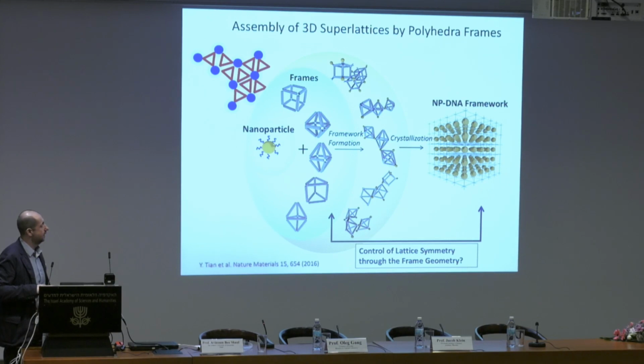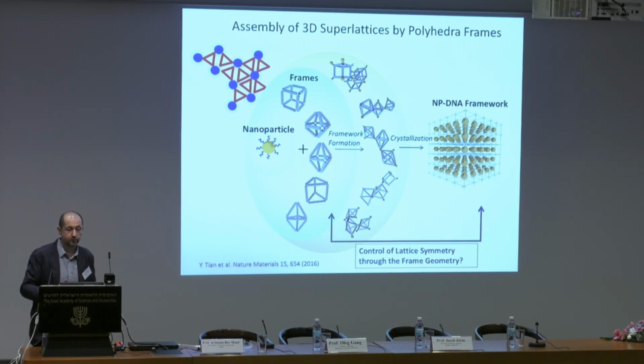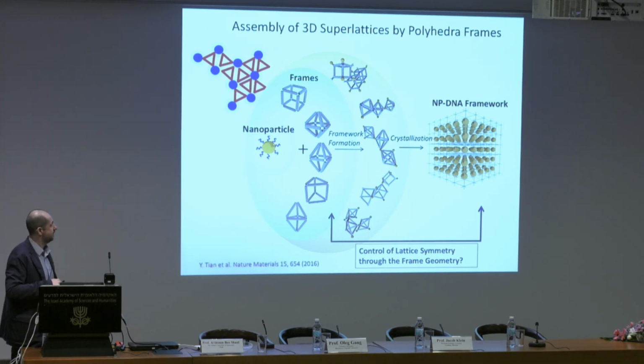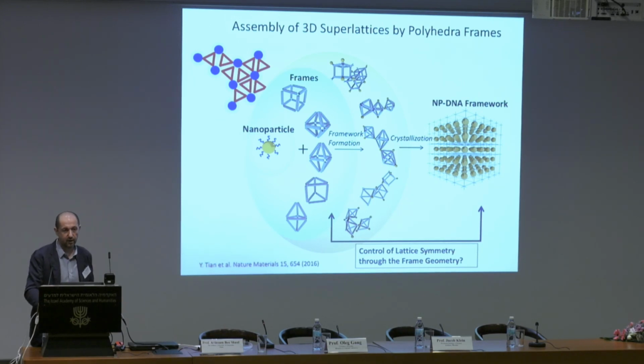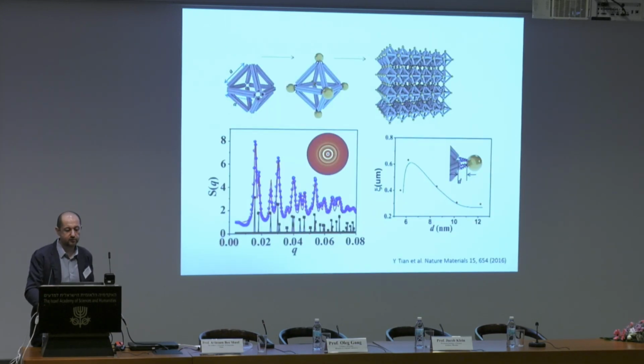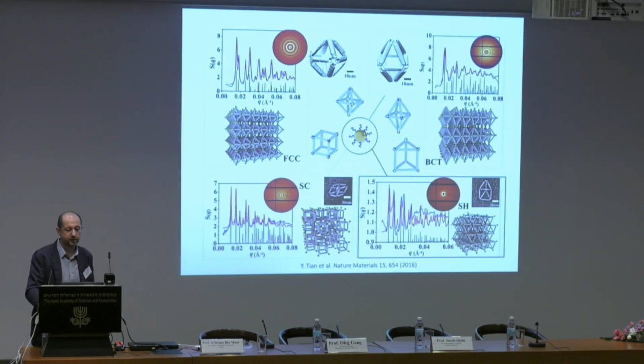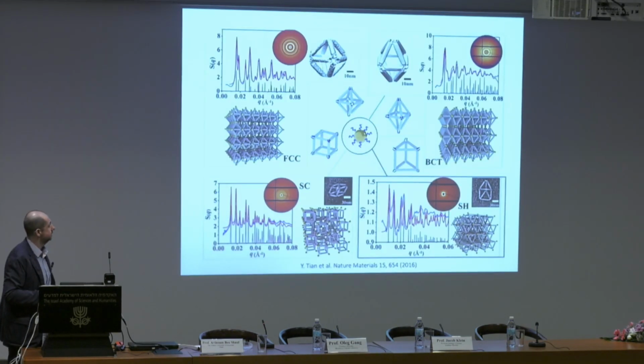Now, again, the underlying hypothesis here is that the lattice symmetry will be determined by the design of the frame. And so from this point of view, by having the same type of particles and providing different types of frames, we in principle can induce different types of systems. Due to the lack of time, I'm just going to jump a little quicker, and basically show you that indeed this can be realized in different types of lattices from the spherical particles by having all these kinds of frames provided, as we can confirm by X-ray scattering.